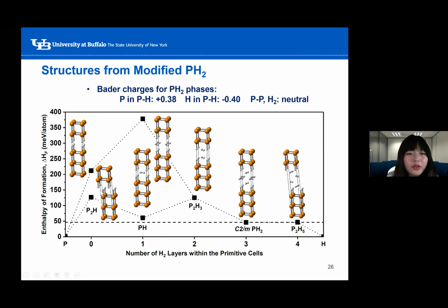If we compare the two structures of P2H constructed by removing all of the molecular hydrogen layers, we find that if we put the PH bonds pointing directly at each other, the structure is significantly destabilized due to the increased volume and the Coulomb repulsion between the atomic hydrogens. And if we compare the two structures for PH, we find that if we insert the molecular hydrogens directly in between the PH bonds, the increased volume also